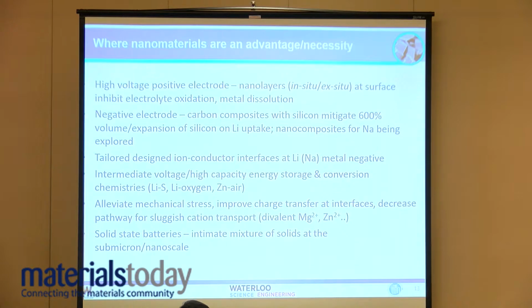I already mentioned high voltage materials only work, these metal oxides, because effectively there are additives in the electrolyte that passivate the surface and form thin layers of a polymer which prevents further reactivity and also metal dissolution. At the negative electrode, there's been an awful lot of work done on combining silicon nanoparticles with carbon to increase the lithium uptake. And as we heard yesterday, if you were present in the audience, nanocomposites for sodium electrodes are